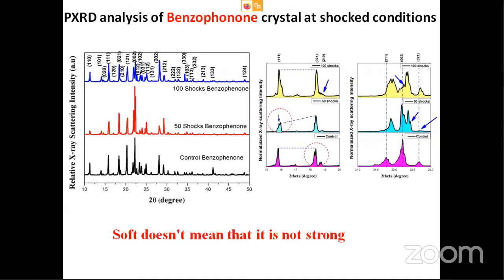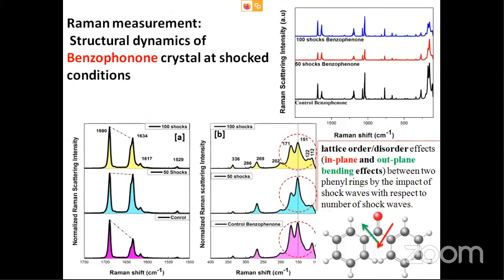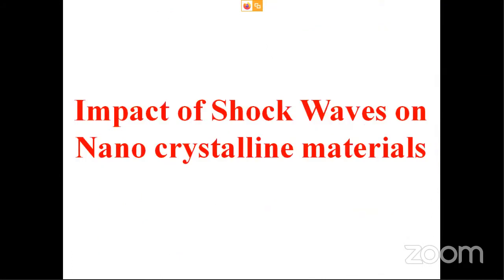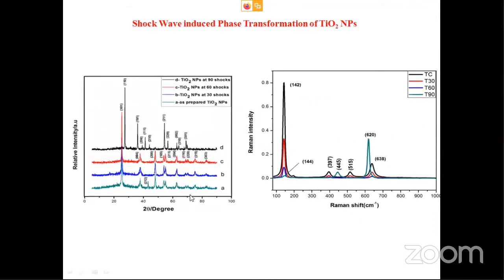Now we can discuss crystalline materials. We have taken titanium oxide nanomaterial crystals and shocked them. This is the XRD of the control. We have given 30 shocks, 60 shocks and 90 shocks. After each 30 shocks, we took the sample to the XRD: first the control, then 30 shocks, then XRD, then 60 shocks, then XRD, then 90 shocks and XRD.